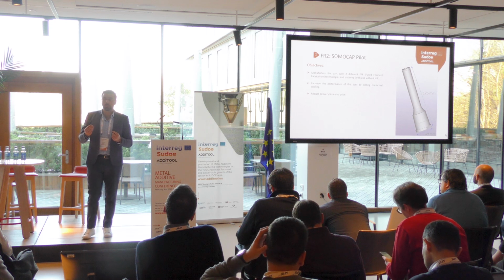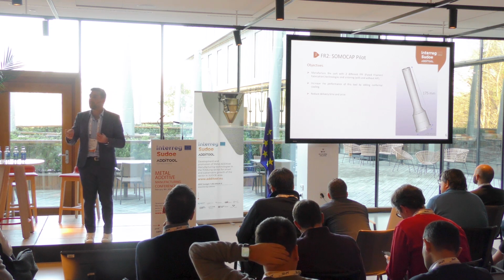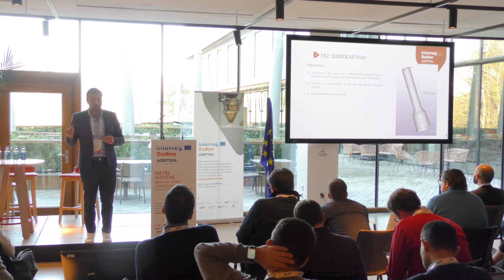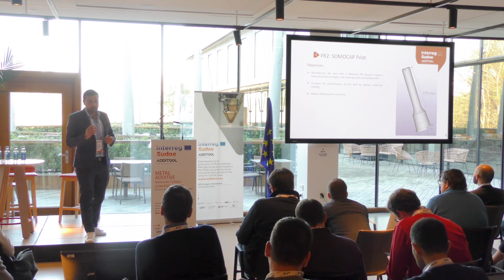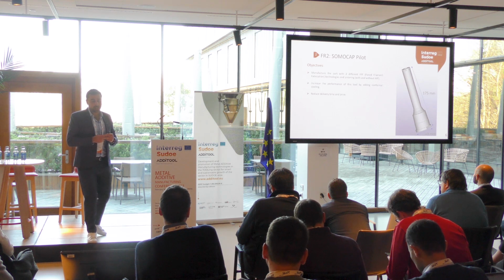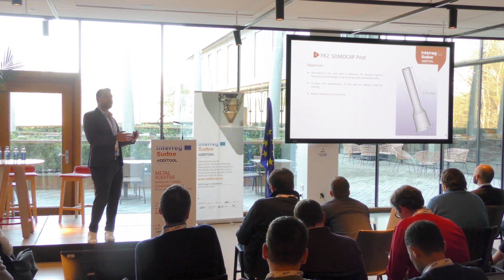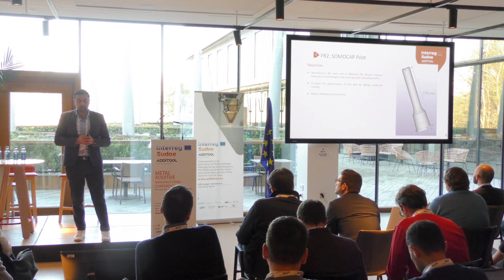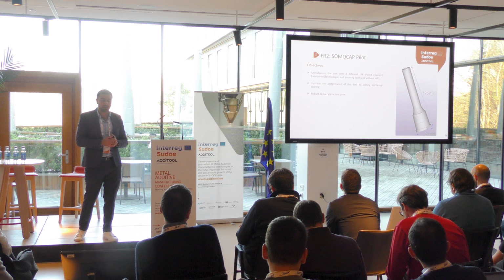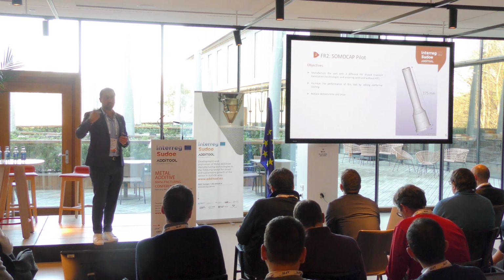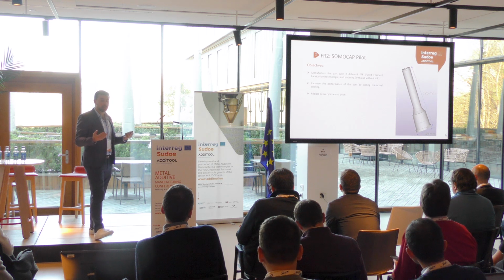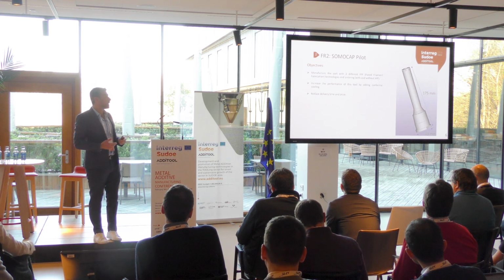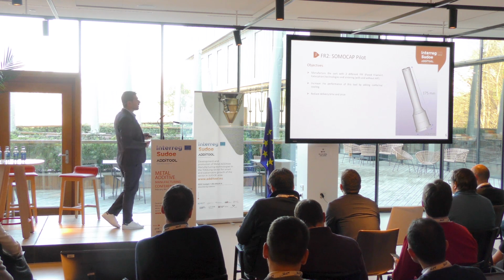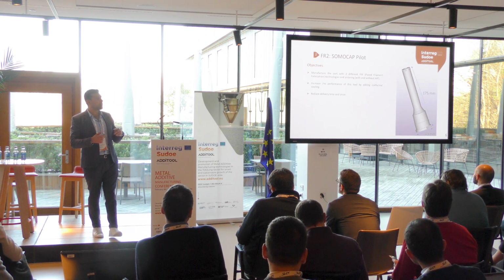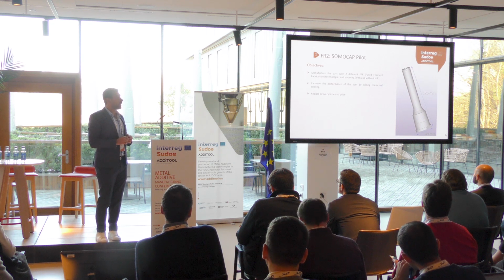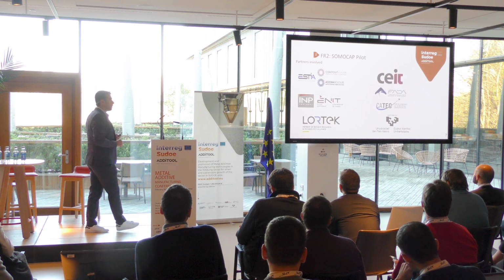The objective is to compare the conventional machine, like a Markforged, and an open system. So with two filament fabrication technologies, sintered with and without HIP, hot isostatic pressing. Also, we have to increase the performance of this tool by adding conformal cooling channels inside, and if possible, reduce delivery time and the price. And just keep in mind that the part is about 200 millimeters high. Okay, that could be a limitation for this technology.